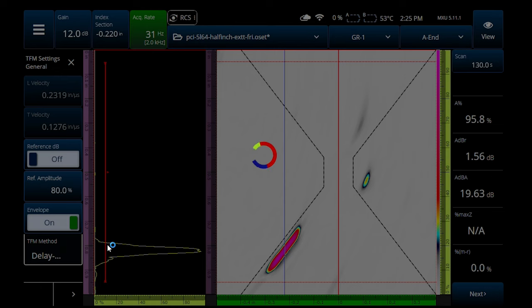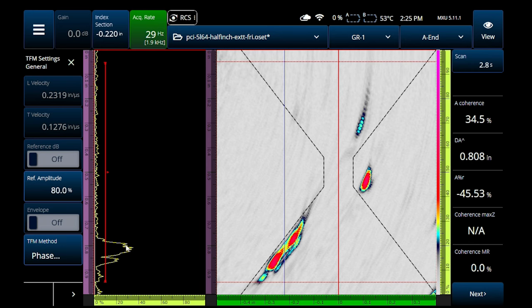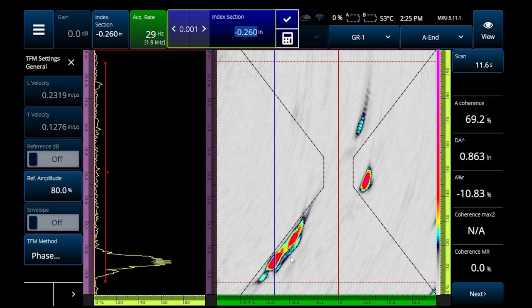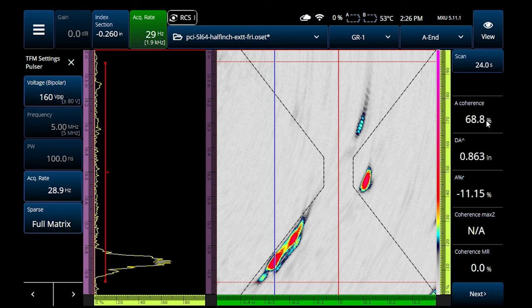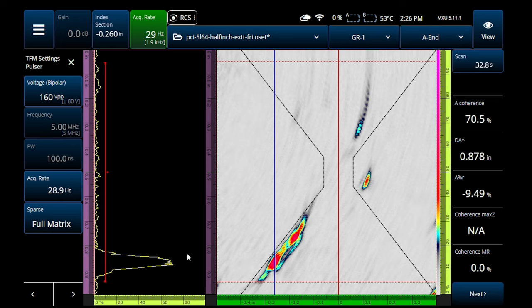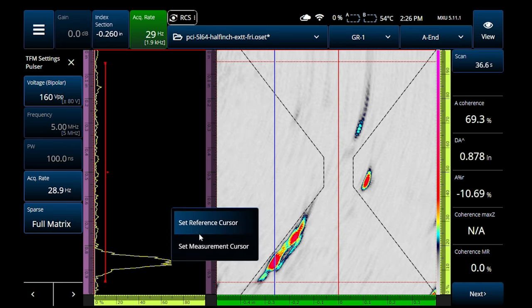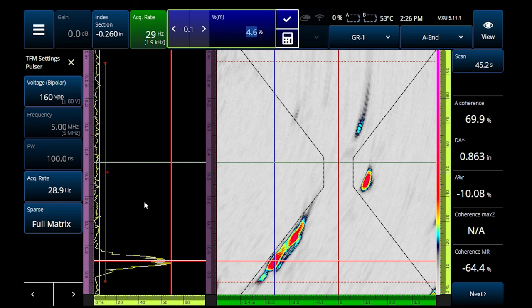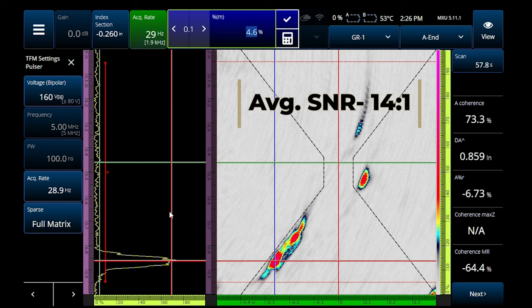So let's see how this one looks with phase coherence. Phase coherence is going to be amplitude-free — it's independent of any gain, it's just based on your voltage. Looking at the highest energy response I'm getting, this is not about more amplitude; this is just more coherence right here. I've got almost 70% of all my elementary A-scans — and I am running full matrix capture — showing coherence right here on the edge of this flaw, giving me a nice bright signal. One cursor is at about 70% and the other is down there at about 5%, so you can figure out the signal-to-noise ratio there.